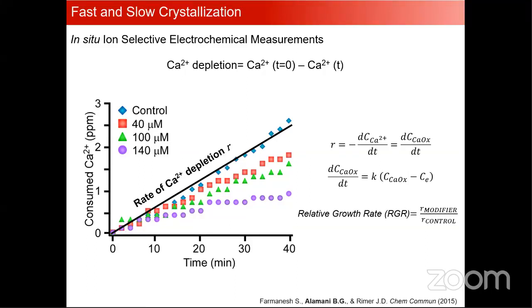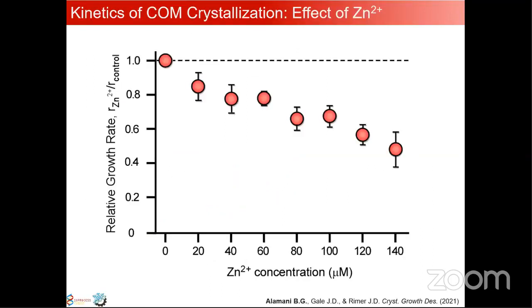We represented this in terms of a relative growth rate, which is the ratio of the crystallization rate to that in the absence of zinc. You start with 1, which is your control, and then it slowly goes down until it reaches about 50% at 140 micromolar, about a 50% reduction. This suggests that zinc reduces the growth rate of the calcium oxalate we are trying to grow in vitro. So zinc can influence nucleation, and it can also influence growth, but at the same time it tends to promote the formation of intergrowth. All of these observations are consistent with what has been published in the medical literature.